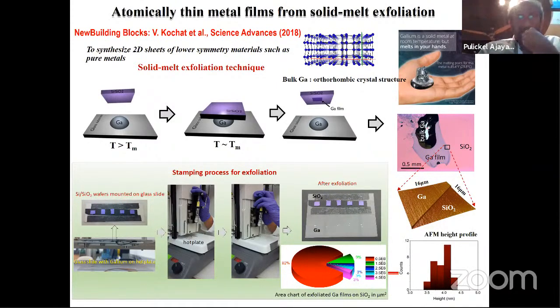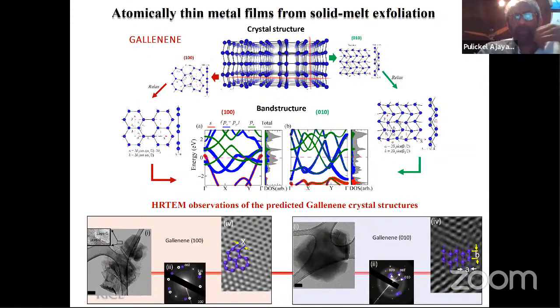What you're seeing here in this case is actually a solid melt exfoliation technique, where gallium, which becomes molten at reasonable temperatures, one could go with the substrate and pick up super thin layers and then explore those gallium layers. We actually called it gallenene. And you can see that, again, this retains the metallic nature of gallium. In fact, there are not too many systems that are truly metallic when it comes to 2D systems. So this was an interesting structure which possibly could have applications as contacts and so on and so forth.